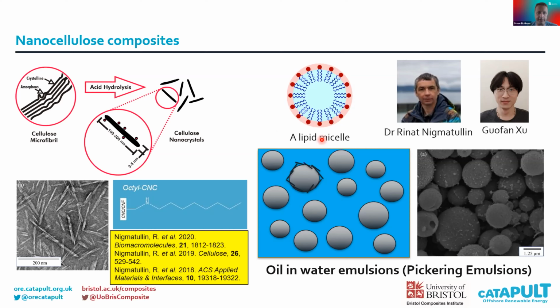But you could do this in a composite as well, and we do this using what's called a Pickering emulsion, which is an emulsion here, but where we use a solid phase for the emulsifying. So we use these octyl CNCs, and they'll sit at the oil-water interface. But we can encapsulate all kinds of oils in here. We can use water-based polymers in here. You can do the reverse, where you have a water in oil emulsion, but this enables us to make these capsules here, and the cellulose nanocrystals sit at the surface here.